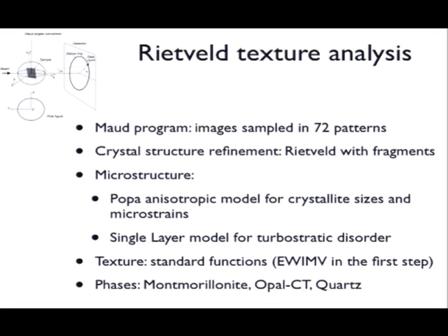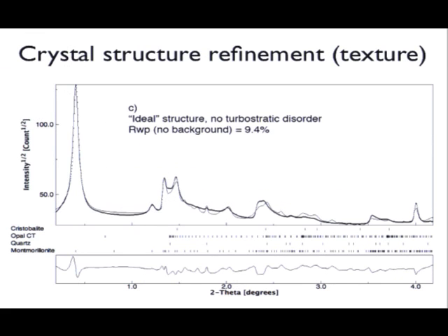Okay? There were 3 phases, oh, actually 4. I forgot the Cristobalite, so we had to quantify also them. So if you start, you put the ideal structure, okay, and you just use only anisotropic broadening, then you don't get a very good fitting. Texture turned out very weak. We were not what you expect for a clay that is also in compression.